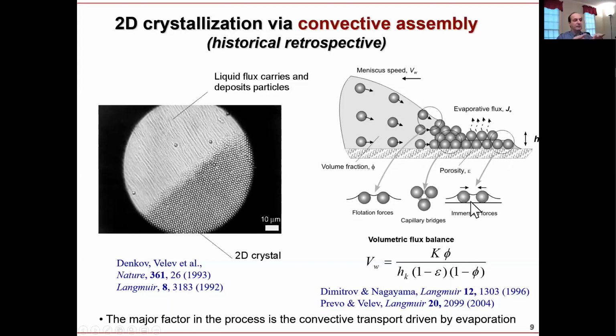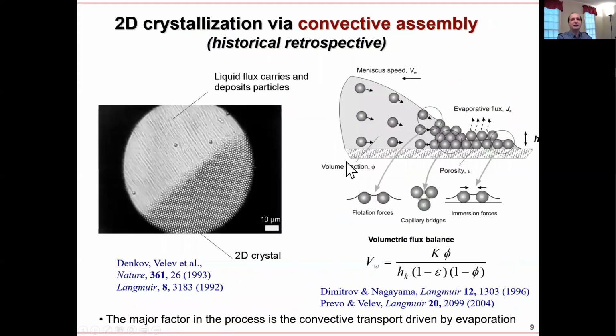And they will be important, but only for a monolayer. So if you have a monolayer, it is very hard to dry, which I constantly get those questions from industry, right? Why, when you dry a suspension of particles, do they not disperse uniformly, but form islands? They form islands because when you dry particles, at the final stage of drying, particles which are close by will be drawn together by the capillary forces, so they will stick together. This is only for a monolayer.